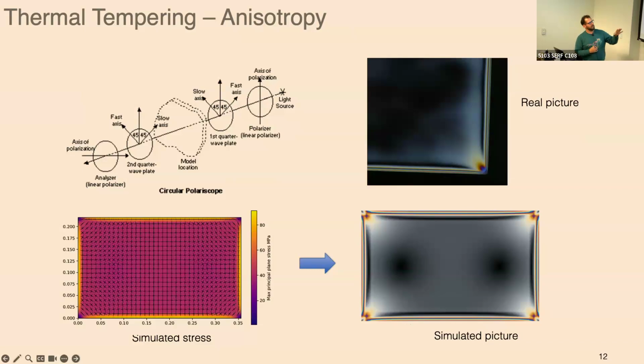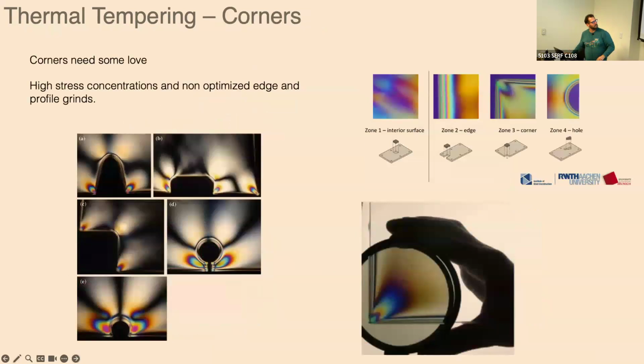If you look at an annealed glass, you'll see high stress points. Especially as you get larger modules, the glass is basically shrinking and pulling in stresses, so you have a bunch of inner material that keeps shrinking. The larger you go, the more distance you have, and it sort of pulls this toward the corners. Now, your module doesn't look curved, but it's not happy. The corners are just not happy in that world.